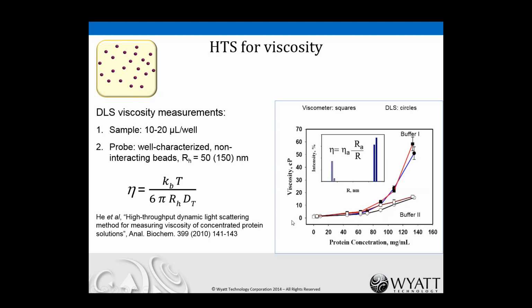Here's a study which was done to assess the correspondence of the viscosities measured by dynamic light scattering and by more standard rheological techniques. And you can see that there's a very nice correspondence. The circles and the squares are two different techniques. The square is the viscometer, and the circles are dynamic light scattering. And these are two different protein solutions, highly concentrated, going up to 140 mg per mL, and still we have some very nice correspondence.